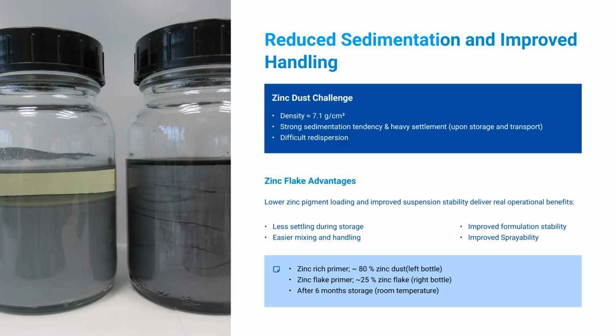One practical challenge with traditional zinc-rich primers is sedimentation. Zinc dust has a high density of approximately 7.1 grams per cubic centimeter, which causes strong settling during storage and transport. This can lead to hard sediment formation and difficult redispersion before application. Because zinc flake systems use substantially lower zinc concentrations, suspension stability is greatly improved. This results in easier handling, improved storage stability, and simpler mixing.